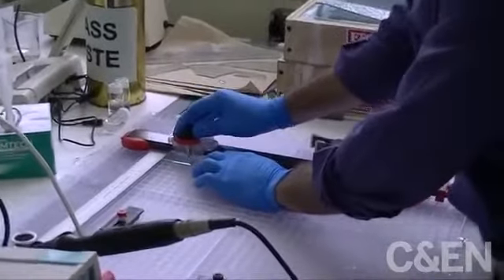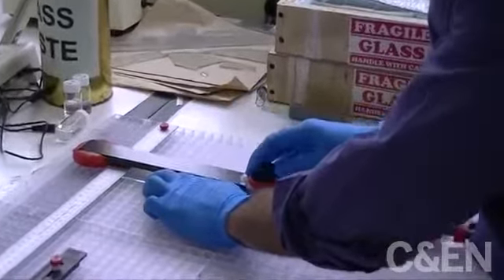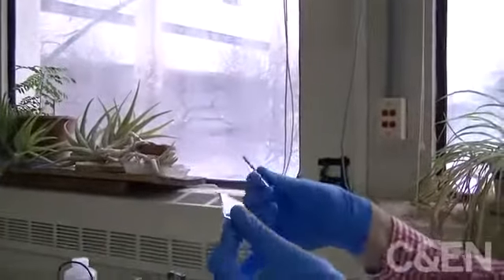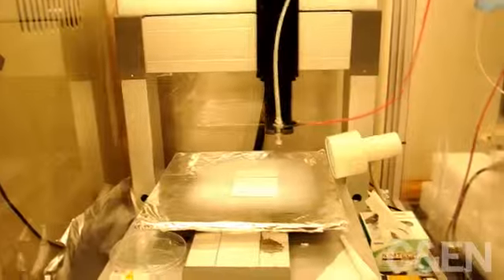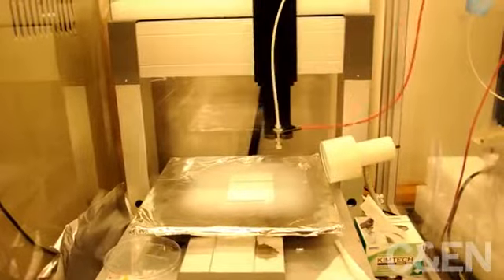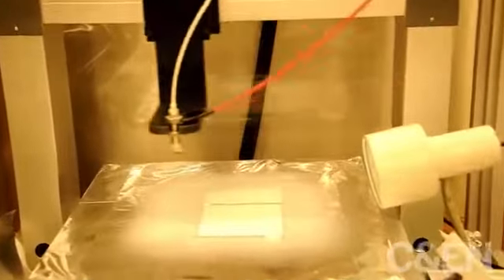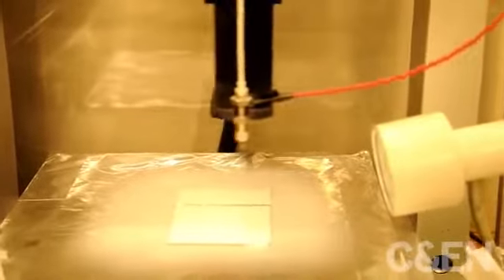These solar cells, or photovoltaic cells, are typically made in a layer-by-layer fashion on a specially coated glass support. This particular lab first treats the coated glass with a dense layer of titanium dioxide to prevent electrical charge generated by sunlight from leaking out of the cell. This robotic arm forms that layer by spraying a titanium dioxide solution onto the glass.